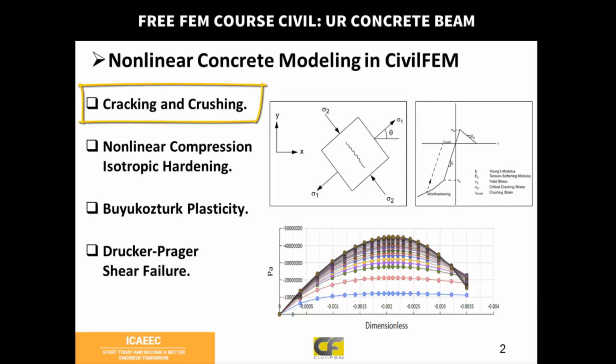Well, first, for concrete modeling, there are different data that must be set. First, for the cracking and crushing behavior. For cracking, we have to input a cracking stress. And after that cracking stress, we can have a brittle behavior, that is, a sudden loss of stiffness. We can add a softening modulus, and also we can add, through a table, hardening and softening for modeling fiber